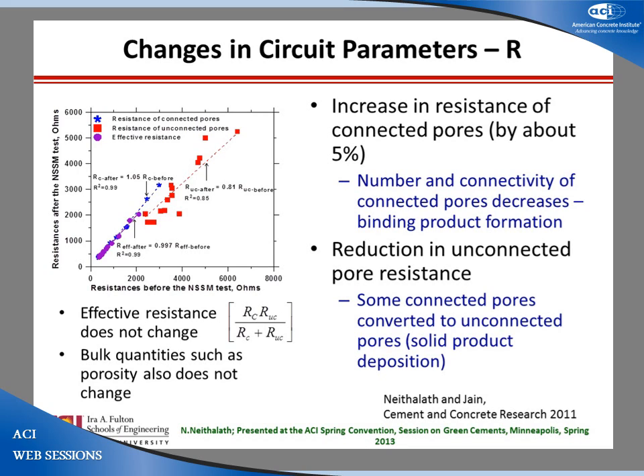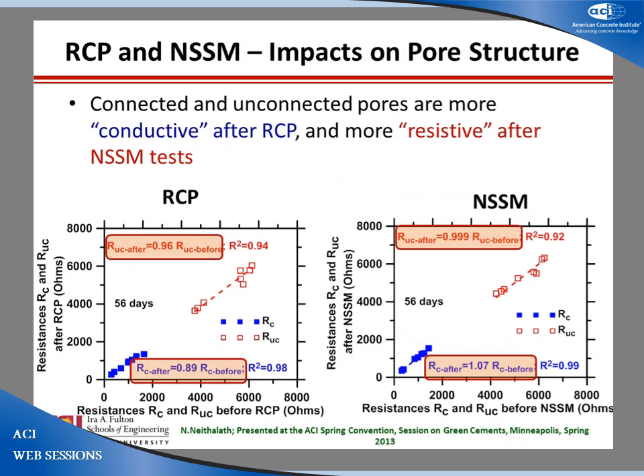The same idea that I told earlier, that you have changes in connectivity, consequently pore sizes, and the reduction in connected pore resistance because some of the connected pores are converted to unconnected pores because solid products started to deposit. So we use this simple model to show what happens in resistance. And with that, we can explain what is happening here. So before and after, with non-steady state migration before and after. So connected and unconnected pores are more conductive after chloride transport, but more resistive.